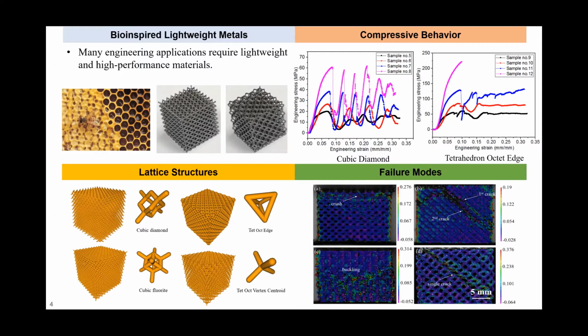As you can see from these slides, we designed and fabricated a few so-called lattice structures as shown right here. And you can see these lattice structures are quite complex. It's almost impossible to fabricate these complex lattice structures using conventional manufacturing processes such as milling, turning, or injection molding. You can see we fabricated various different structures using so-called unit cells. Here I only show 4 different unit cell types, such as cubic diamond, cubic fluorite, and tetrahedral octet edge. And these 4 unit cell structures are only 4 of many different unit cell structures.